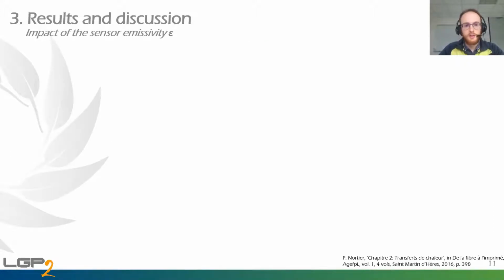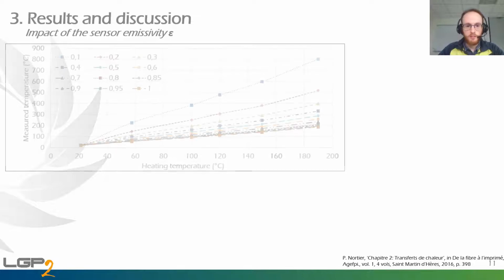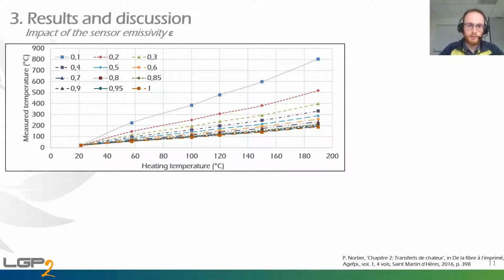Concerning the emissivity epsilon, we have also an important impact to check. Here the same figures as before, but h and theta are fixed, and the emissivity will be set between 0.1 to 1. As you can see, we can have big differences between heating and measured temperatures. For example, at high temperatures, we have nearly differences of 600 Celsius degrees.